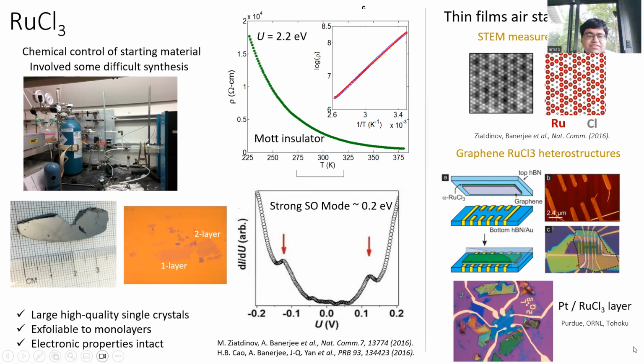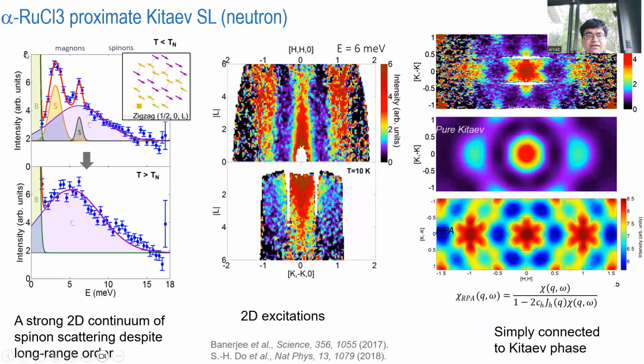So in neutron scattering, one of my earlier results showed this, the intensity versus energy. So you're looking at the density of states. The density of states not only shows these sharp magnon modes, which are the bosonic modes, you also get this nice band of continuum. And as we know, bands or band structures come from fermions. So when we saw that nice band, we were able to conclude that there is something more happening here, which is that the only way you can get a band there is if you consider that you have Majorana fermions in the system, which are forming these fermionic band structures. And these are magnetic Majorana fermions. So we see them in neutron scattering, and that's what we